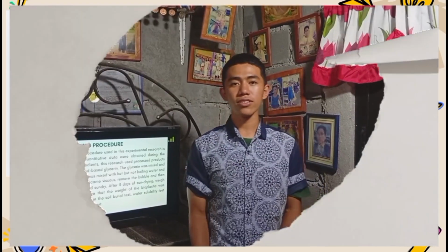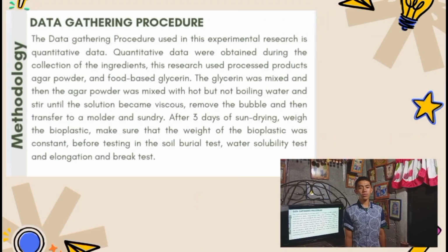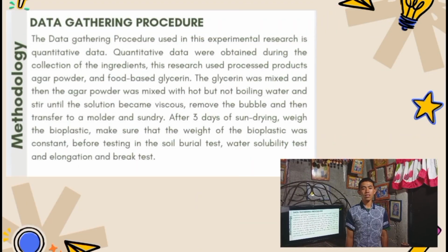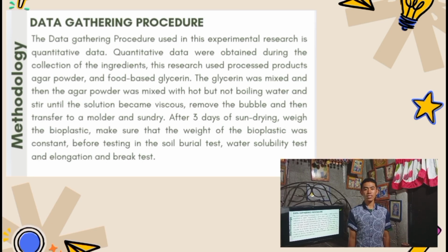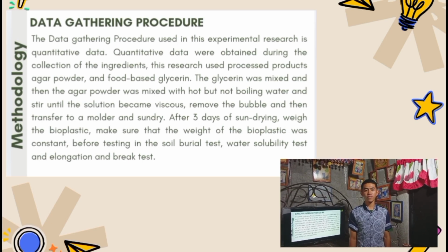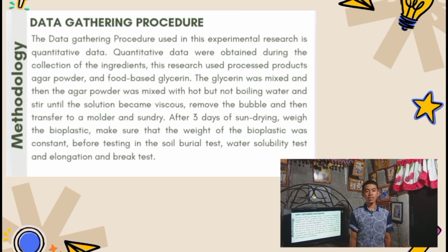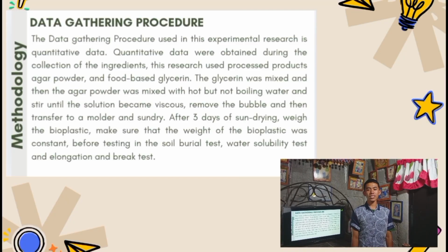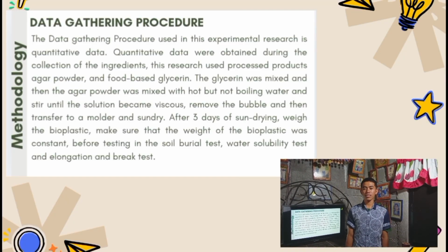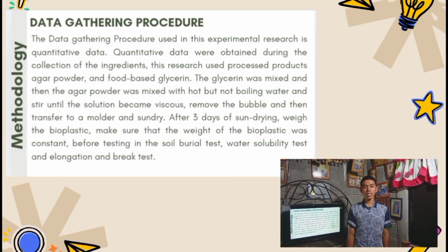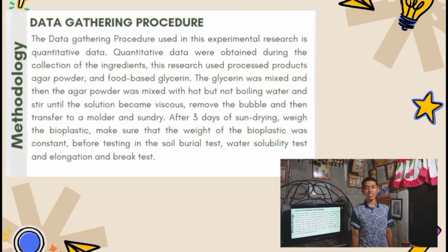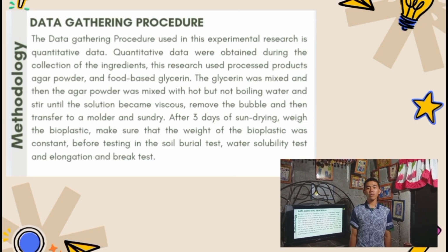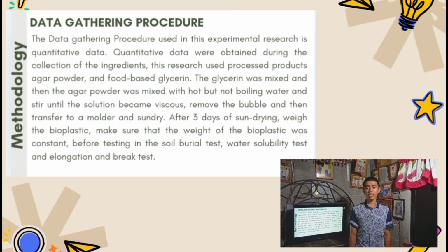Data gathering procedure. The researcher tried to test soil burial test and water solubility test. The bioplastic is buried 7 inches deep in soil for 24 hours, and then the samples are retrieved, cleaned, and sun-dried until they reach a constant weight. And then reweighed to calculate the degradation rate.